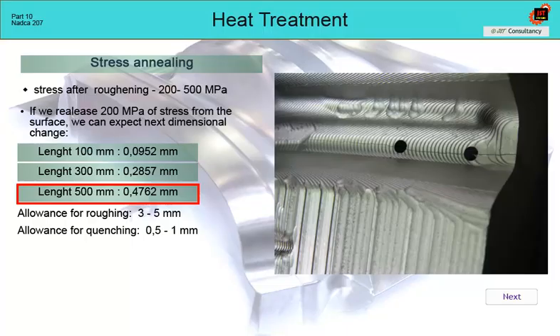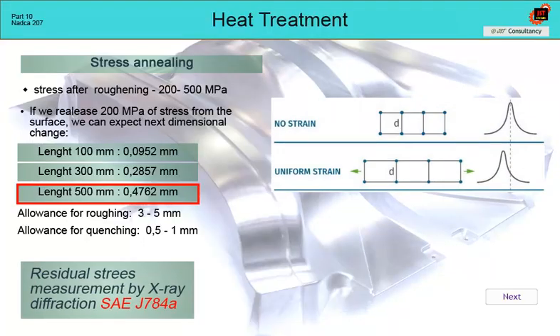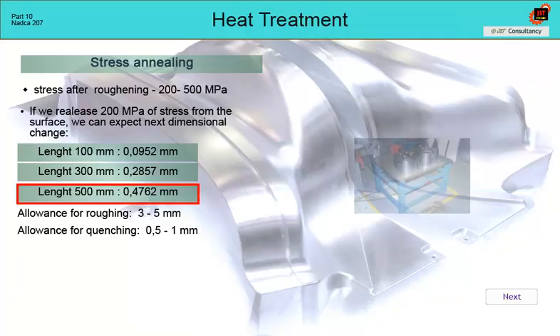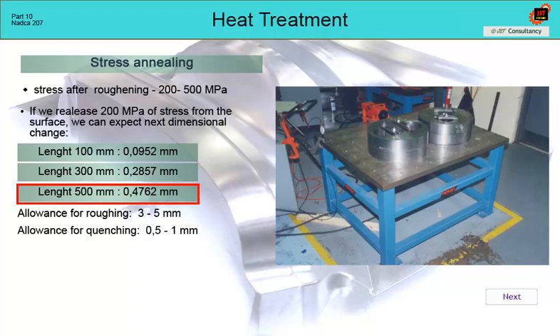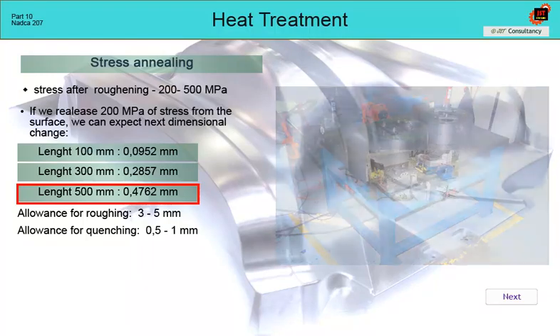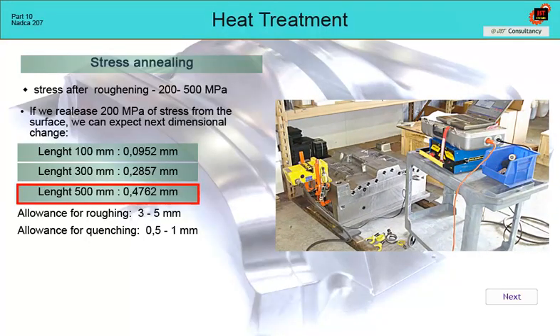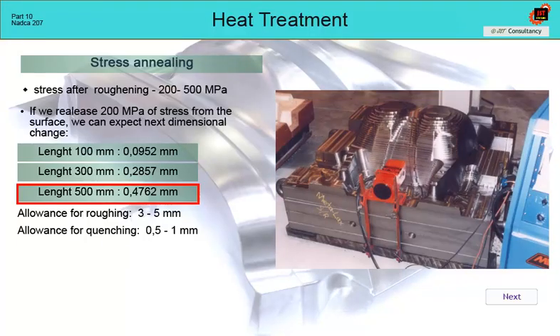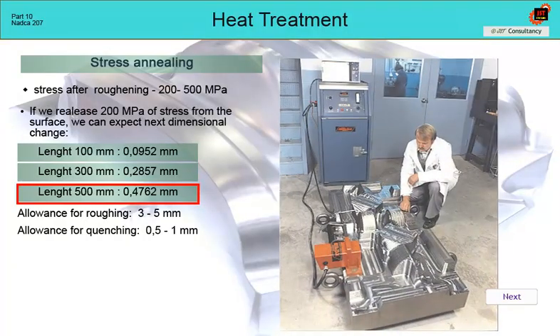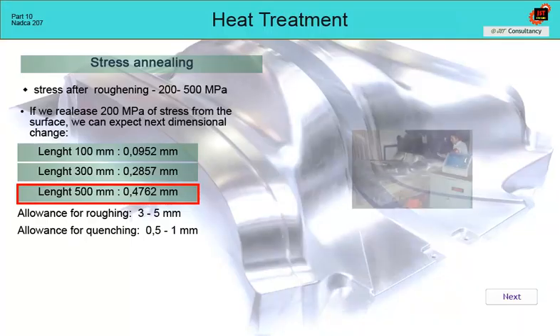If we have doubts, the stress in the surface can be measured by X-ray diffraction, when we can calculate the magnitude of the stress from the shift of the diffraction lines. It can also be determined whether the stresses are tensile or compressive. An alternative method to the thermal process is vibration stress relieving. This method was developed for stress relief in large welded structures for which it is difficult to find the appropriate furnace size. The principle of the method is that the part of the insert on which we need to release the stress is placed on a rigid plate, and rubber silent blocks are placed on it. A vibration pulse generator is placed on the insert, which controls its frequency and is left to act for about 1 hour. Theoretically, this way, stress can also be released, without having to go to the heat treatment shop.